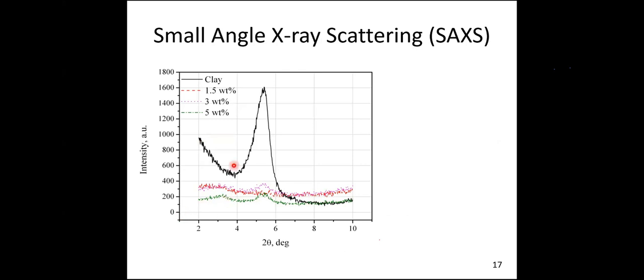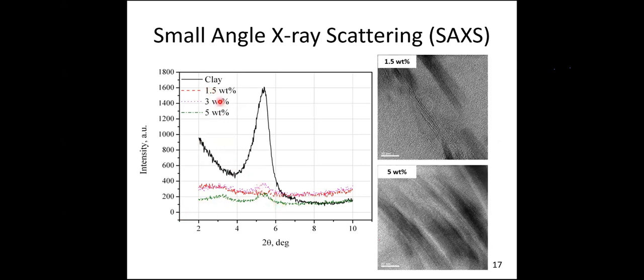So here also you could see that black is clay, and red is 1.5, where 1.5 doesn't have any peak, which means the clay is dispersed well with epoxy. The 3 and 5 have a peak at around 5 degrees, which means the dispersion is not good, it is agglomerated.